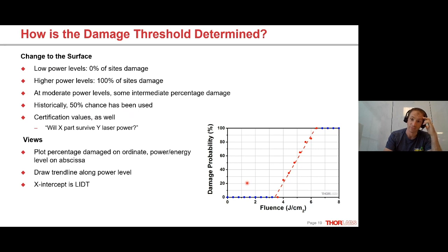Yeah, definitely a good point to keep in mind. So if the laser is polarized, will that affect the damage threshold, or will that reduce the damage threshold? It will always affect the damage threshold, particularly when you're working at non-normal angles of incidence. One of the more interesting papers I remember reading was on the damage threshold of a thin film polarizer that's designed to transmit P polarization and reflect S. This paper had a number of different methods, and one method would produce a high result for transmitting P, and another method would produce a high result for reflecting S. So yes, that's something you're going to have to bear in mind for non-normal angles of incidence.